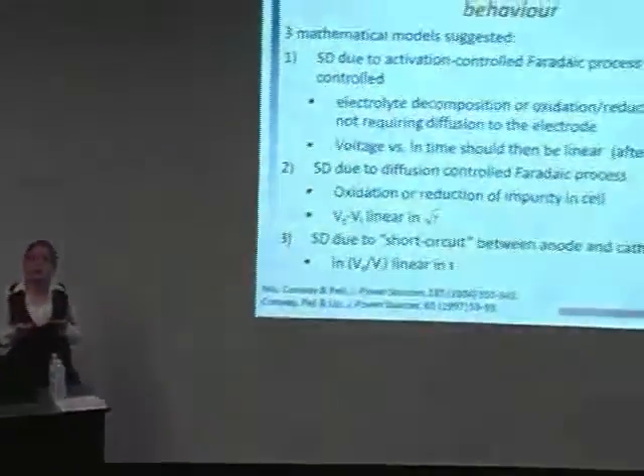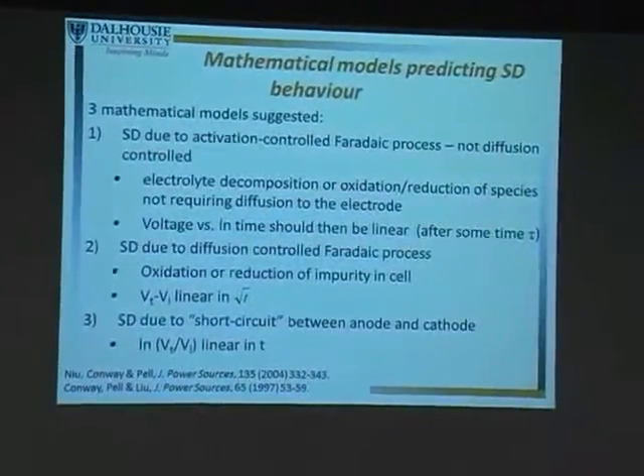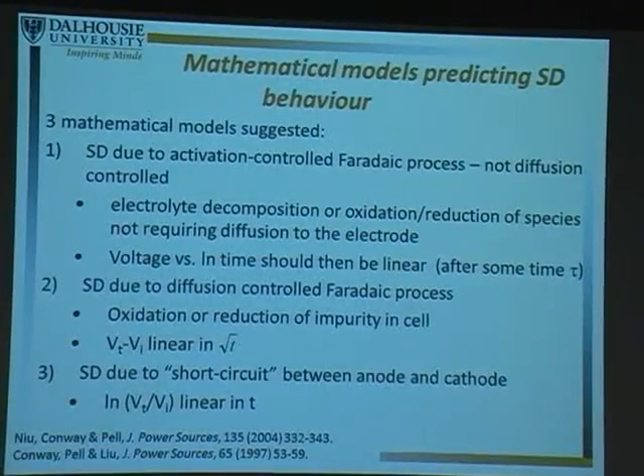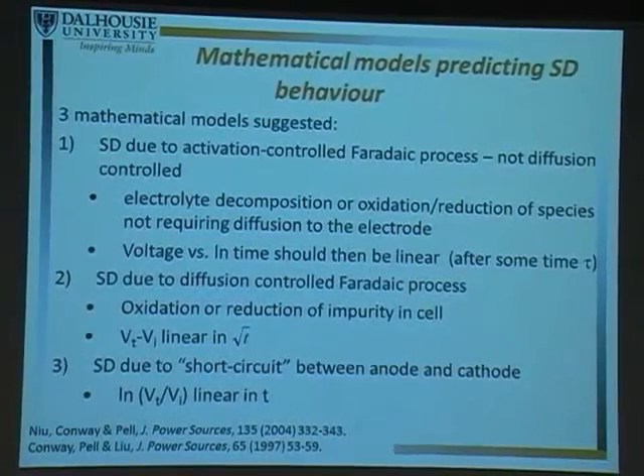What this means is that your reactant is at a high enough concentration that we don't have to wait for diffusion. So this might be something like electrolyte decomposition, very high concentration. We don't have to wait for our species to diffuse to the surface. Alternately, it could be something that's attached to the surface, so again, you don't have to wait for diffusion, or it could be the reaction of the surface itself. And so any of those possible situations would result in an activation-controlled Faradaic process. And we can identify an activation-controlled Faradaic process by plotting the self-discharge profile as a function of log time. And when we do that, what we will expect to see if it's activation-controlled is a plateau and then a linear drop in potential.